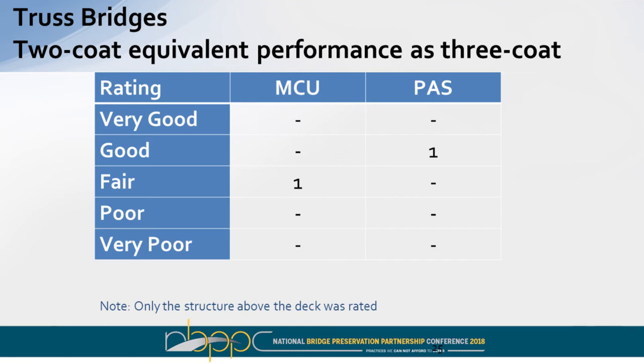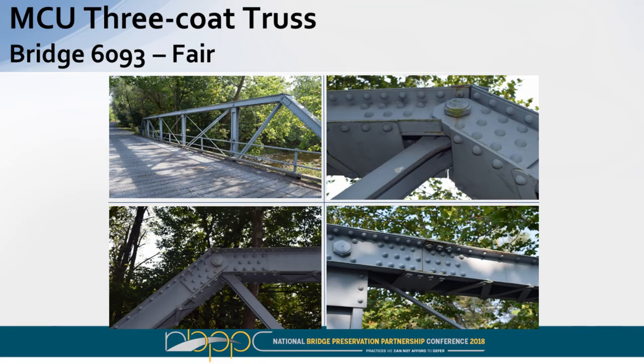In the truss bridge structures, the polyaspartic bridge was rated good. The moisture-cured urethane bridge was rated fair. We only really were able to get to these structures from the deck up was all we rated. We didn't have access to down underneath them. This is the three-coat truss bridge that we rated in fair condition. A little bit of corrosion around some plates and things like that.